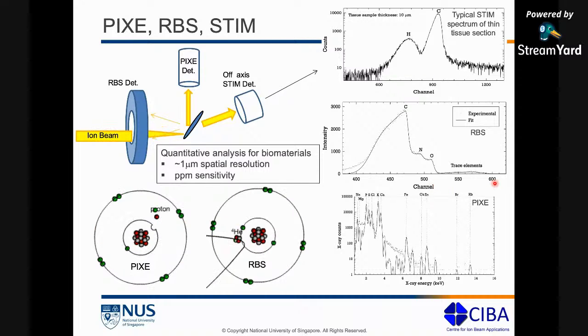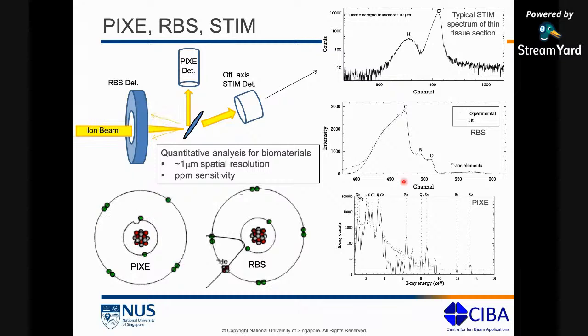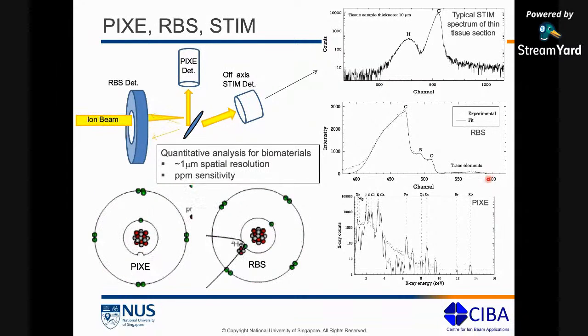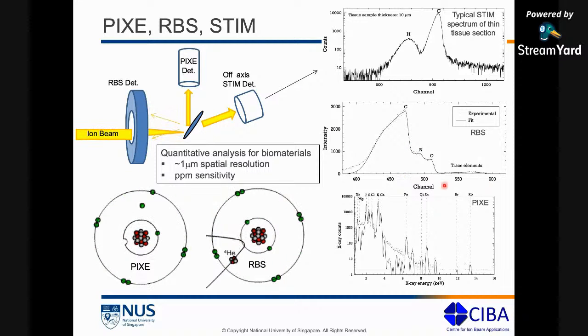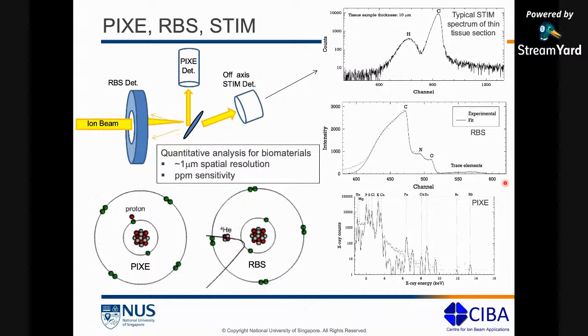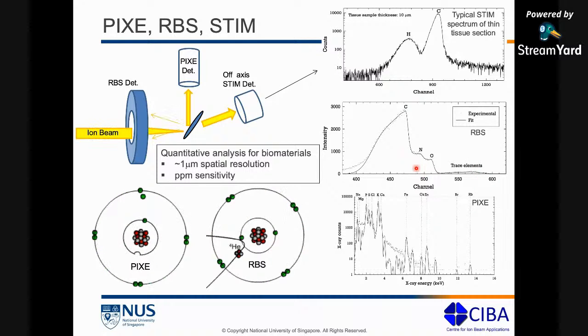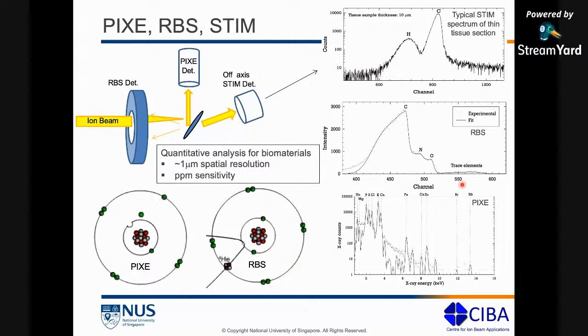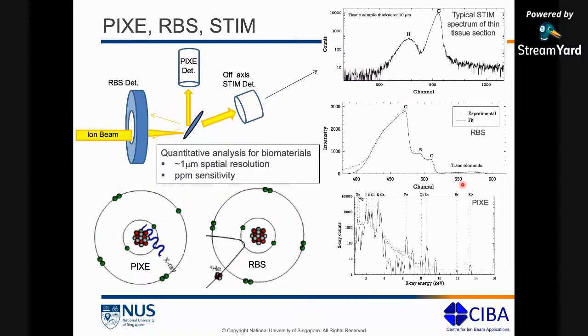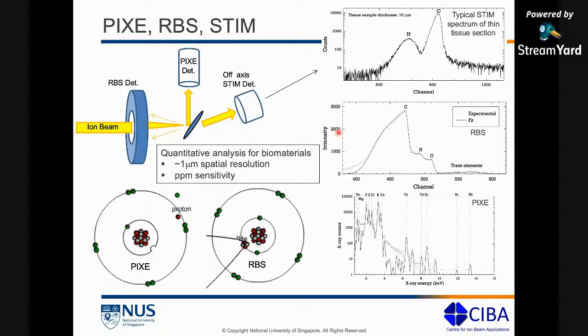So going from high energy to lower energy, we can have heavy elements coming out at higher energy and lighter elements coming out at lower energy. The energy scale also gives you an idea of the depth. So if you have a single thick sample, the backscattered energy from the surface will be much higher than the backscattered energy from deeper inside. So the energy scale can also be converted to a depth scale if you have a thick sample. So the surface energy will be higher compared to the energy coming from the bulk of the sample. Okay, so that's what a typical RBS spectrum looks like.